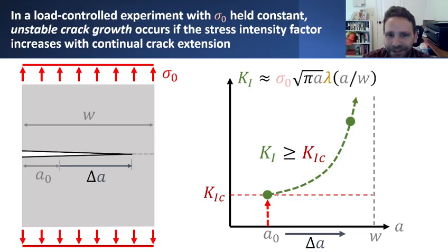It's where small increases in crack size lead to corresponding increases in the stress intensity factor. And that feedback loop then leads to continuation of crack growth in this totally uncontrolled way that leads to catastrophic and very sudden failure of the entire specimen. Now, that's not descriptive of all scenarios in which crack growth occurs. There are certainly other types of scenarios, as you might guess, stable crack growth scenarios, in which a small increase in crack length doesn't necessarily lead to an increase in stress intensity factor. And so you might be able to actually see the crack grow little by little as you try to increase the loading applied to the specimen. It all depends on how you've designed the specimen and how you're assigning the loading.